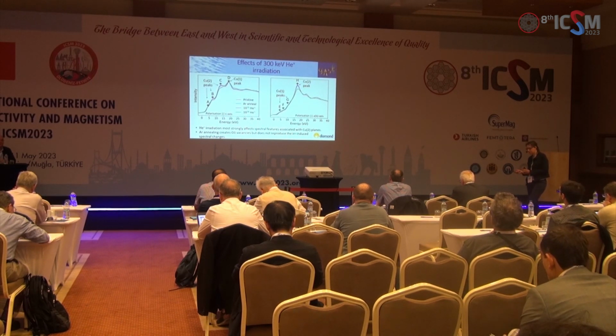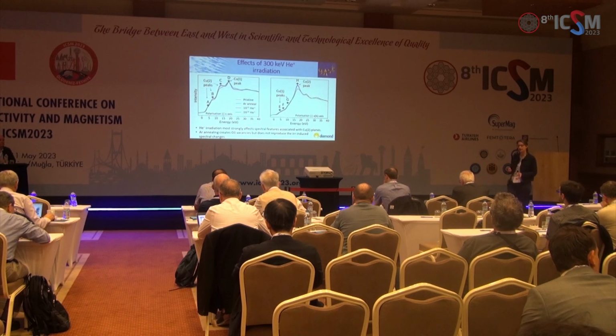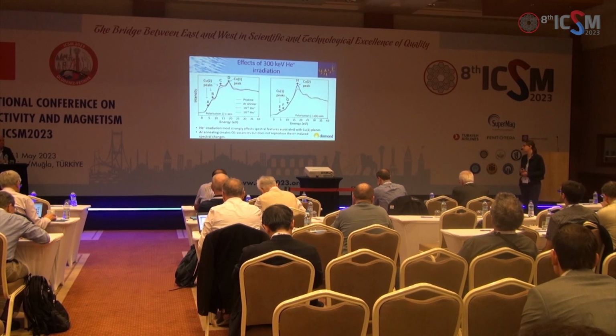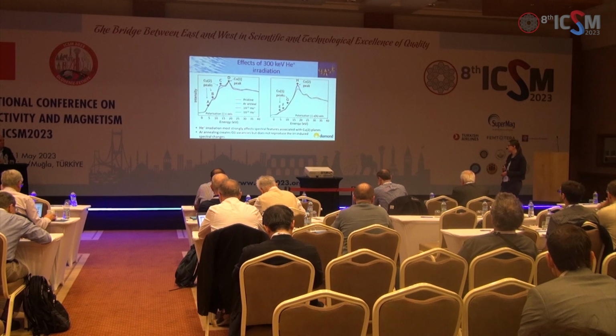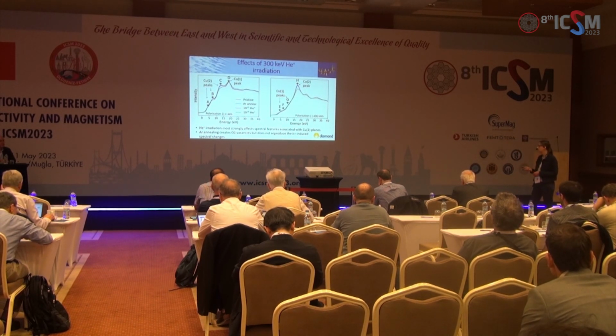To compare with, we've looked at some samples that have been argon annealed instead of irradiated, because with argon annealing, we know we pull out oxygen, and we know where from the structure that oxygen comes out. It comes out from what we call the O1 sites. And so we're using that as a little bit of a comparison for our model.